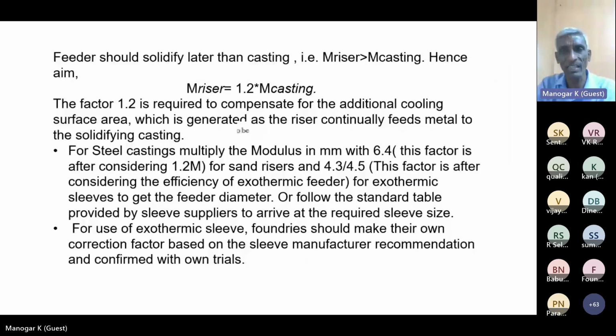The feeder should solidify later than the casting, that is, the modulus of the riser should be greater than the modulus of the casting. The factor of 1.2 is required to compensate for the additional cooling surface area which is generated as the riser continually feeds metal to the solidifying casting. For steel casting, multiply the modulus in mm by 6.4 for a sand riser, and 4.3 to 5 depending upon the sleeve efficiency which you have arrived at in your foundry for exothermic sleeves. Follow the standard table provided by the sleeve supplier, and do not use one supplier's sleeve standard with another and get confused.